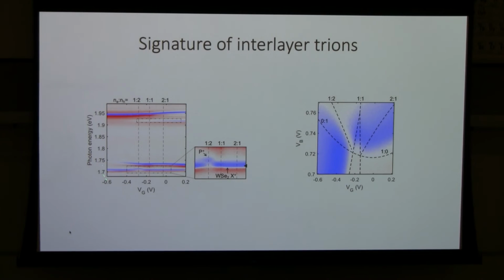So first, I just reproduce the spectral feature. What you can see is the intralayer trion peak, which we call the X plus peak, disappears here, but then a new peak appears. This corresponds to one line cut in this bias voltage and gate voltage phase diagram. We can also focus on only one wavelength, say just at this X plus wavelength, and look at its behavior in this two-dimensional phase diagram. What we can see is this intralayer trion signal is present almost everywhere when you have hole doping in the system, except along this 1 to 2 line. So it really tells us this spectral feature is associated with a specific doping ratio between electrons and holes. So something is happening at that filling.